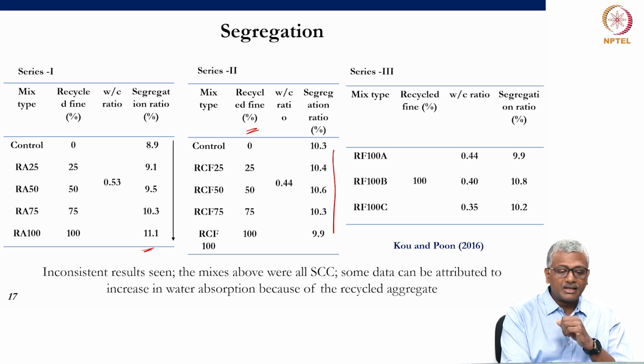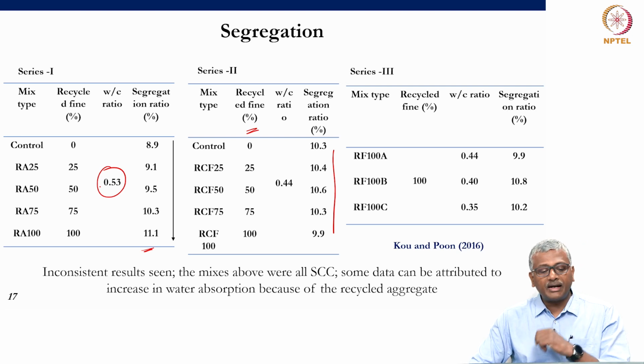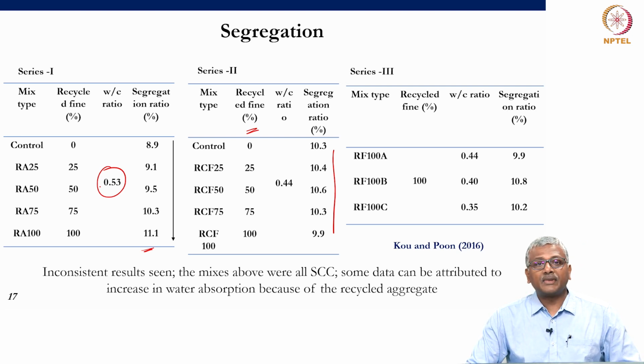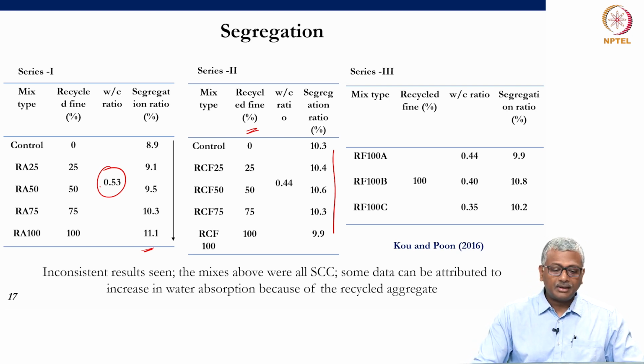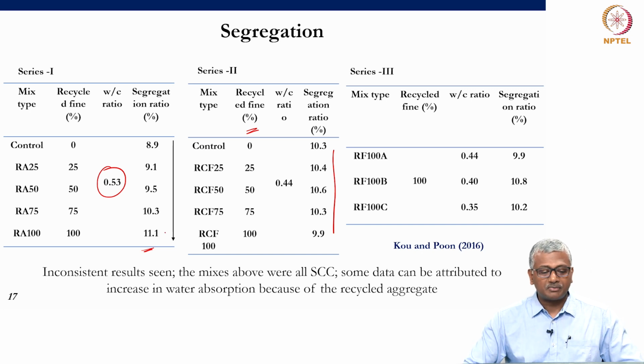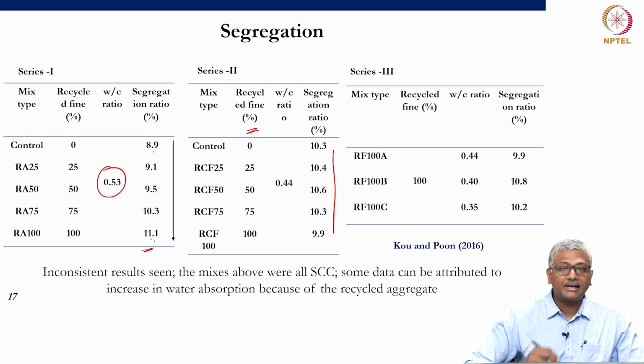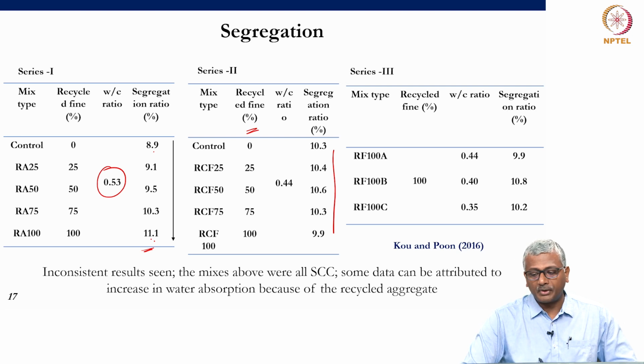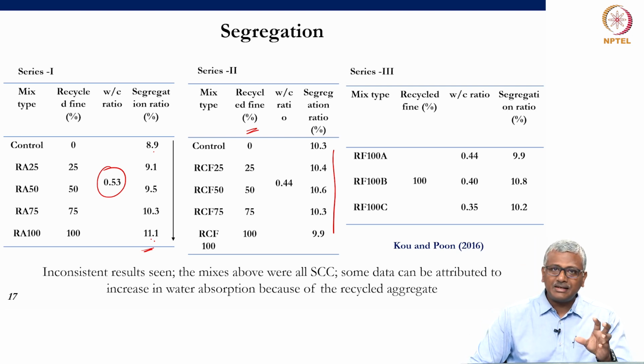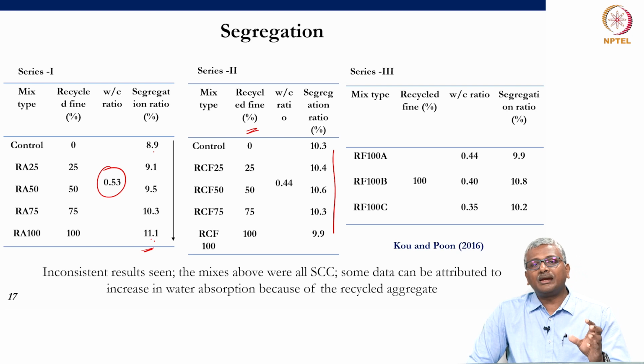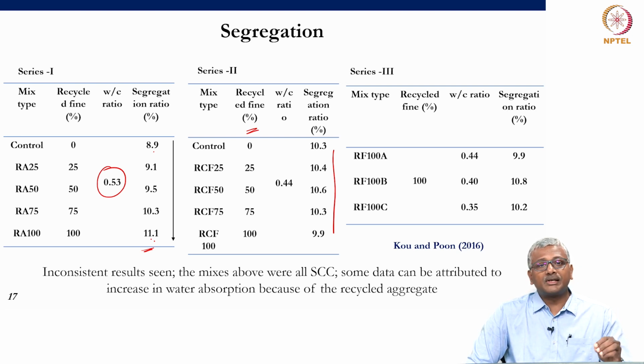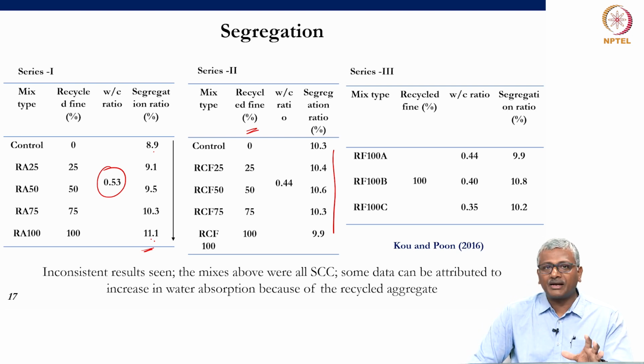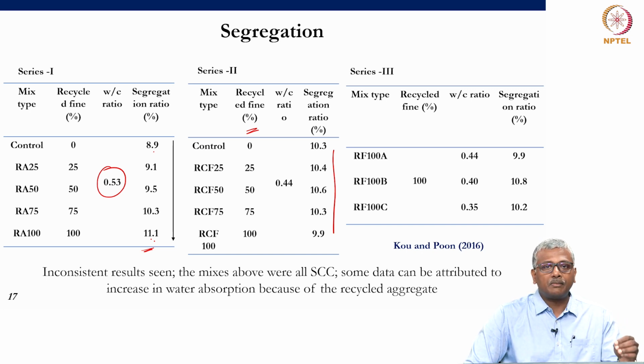But in one more case, at higher water cement ratio, they found that with increase in the extent of recycled fine aggregate, the segregation ratio increased, but it is still going between only 8.9 and 11.1. It's not really that much. Okay, so results seem to indicate that the segregation ratio does not really get altered significantly when conventional aggregates are replaced by recycled concrete aggregates.